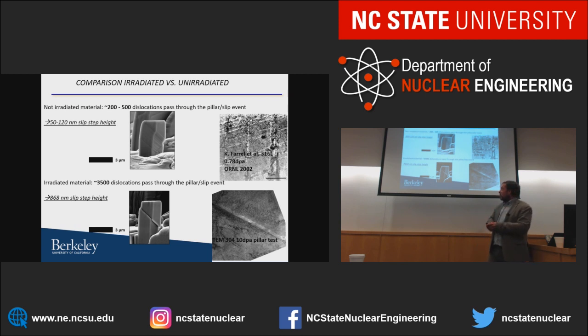And as you do that often enough, you create channels which actually have no defects in them. And so now you have a strong material and a small channel with all the soft stuff in it, and all the deformation is going to happen in the soft region, leading to the fact that you only see deformation in a couple of very distinct channels. Now, macroscopically, that would be a very brittle failure, right? Because all your plasticity, all the deformation happens in a nanometer-sized regime, versus normally the entire body would participate in that deformation. And so doing this microscale testing tells us a lot about the deformation mode these irradiated displacement damaged materials are in.